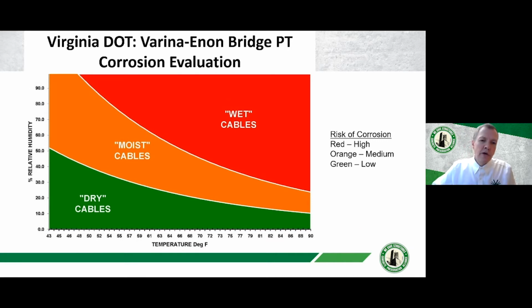The picture that you just saw was from this particular bridge, and it had a history. They had one tendon fail in this bridge, and we tested 4 other tendons, and we got basically 4 measurements that were all up here. There may be other tendons that are not as wet or don't have as high a risk of corrosion as the 4 that we measured, but this is certainly probably one of the reasons why they had the corrosion issue that they did in the one tendon that failed.